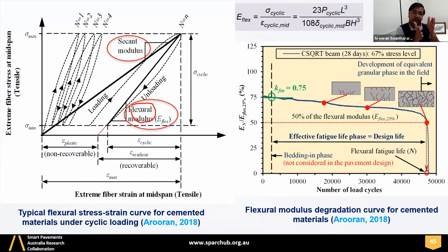And what happens during the cyclic loading in the four-point bending is again the plastic deformation. Plastic deformation increases, or permanent deformation, or progressive damage happens as number of load cycles increases. So flexural modulus is the input parameter for cement-treated base design, and how it varies with the cycles. So flexural modulus is in the laboratory determined by flexural stress applied in the cyclic manner, and the flexural strain measured using the deflection at the middle of the beam, right?